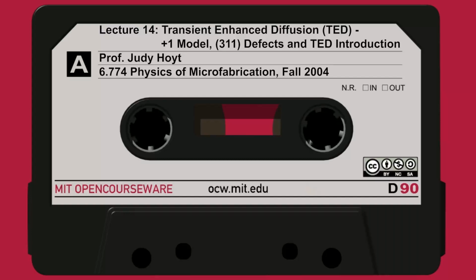It's completely random. So pre-amorphization has two benefits. You can get a little better activation of the boron, and it eliminates ion channeling, so you can do shallower junctions. It costs more money. It takes time. It does create end-of-range damage, so there are trade-offs in using pre-amorphization as a way to do boron implants. So that's mainly what I wanted to say about dopant activation.